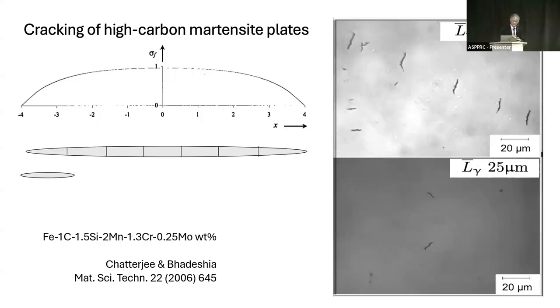So my idea, our idea, when I say my, of course, I've got students working with me, was that, look, when we refine the austenite grain size from 124 micrometers to 25, I get a huge reduction in the number of cracks. And there is some periodicity in the cracks that form in a single martensite plate. So supposing that we use composite theory, if you have a short fiber, then the stress at the ends of the short fiber is not very large, because you can't transfer stress at those points.